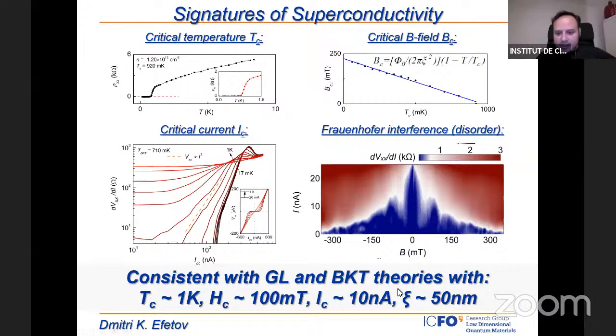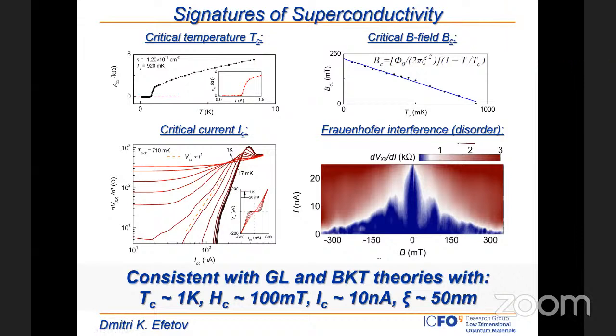Sorry, so Xi we know because we did critical field measurements as a function of temperature and just did Ginzburg-Landau. From this, we extract a Xi of about 50 nanometers. And what is lattice parameter? Yeah, lattice parameter is 14 nanometers. So it's 3 times the lattice parameter.